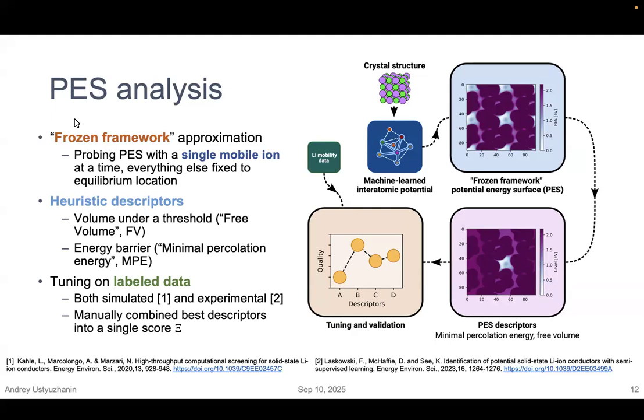And so we had a small data set of labeled data, either simulated or experimental, for which we combined several descriptors or chosen descriptors to predict diffusivity, or predict diffusivity ranking. So we're not interested much in the absolute value of diffusivity here, but we're interested in some kind of relative ranking between diffusivity of different materials.